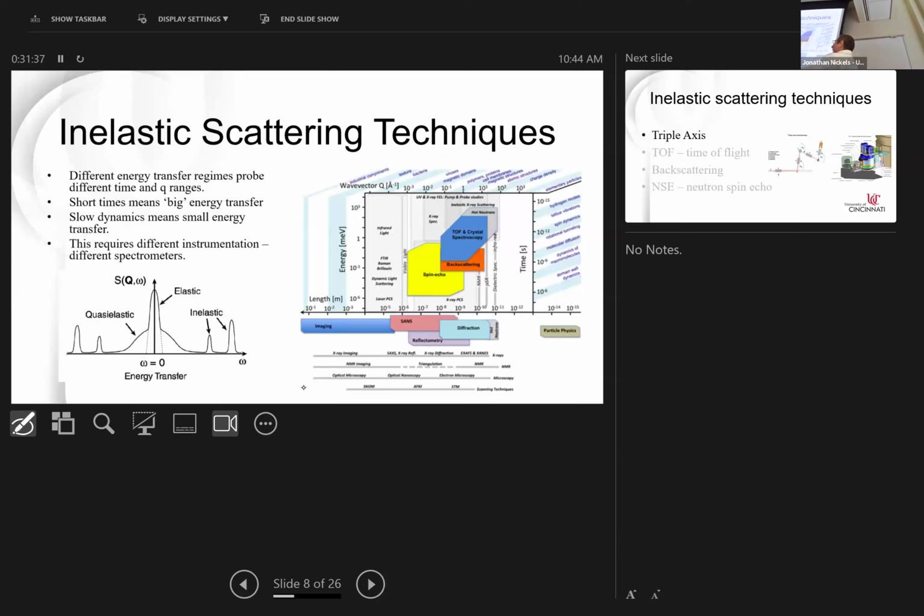So that brings us back to this kind of question. We have different windows of time for different types of broadening in your system. We've talked mostly about slow stuff like Rouse dynamics or chain fluctuations. You can also get peaks out in the very fast dynamics, and those are going to be molecular fluctuations and vibrations. So very much the same things you might see in a Raman experiment or an IR experiment. But sometimes you really need the neutrons to do that.